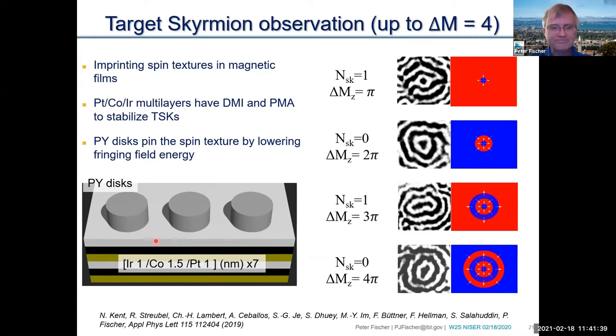The very interesting result was that we were able to identify, in various of these structures underneath these discs, target skyrmions that had multiple rotations of the magnetization. This is just one example, which has one rotation shown, and you just need to look at how many of those circles are closed and when they finally break up. This is how you count: this is one, this is one, two, this is one, two, three, and this is one, two, three, four. And the diameter here is the perimeter of this disc. By varying the size of the disc, we were able to squeeze more of those target skyrmions into the system underneath.